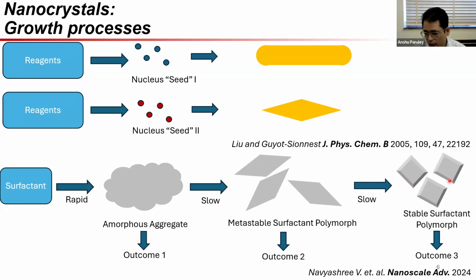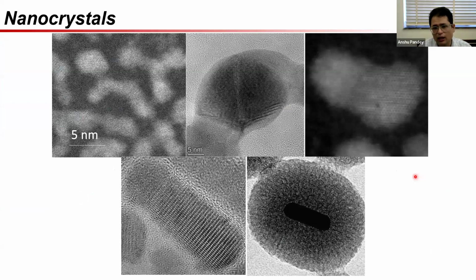But if we slow down things further, we would actually obtain the stable surfactant polymorph, which of course we didn't do, but this would lead to an outcome 3. Nonetheless, we know that the stable surfactant polymorph was there because we could observe the thermal parameters of our metastable polymorph and find out that this was just lurking in the background. And if we waited long enough, we would even get that. So this is just an example of how, in colloidal chemistry, depending on when the reactions are intercepted, one can get totally different outcomes, not just because of the main solid of interest doing its thing, but even the surfactants and all the participating reagents having the same sort of dynamic happening to them. So bottom line is, this is what makes nanoparticles and colloidal chemistry so diverse and gives it so much power.